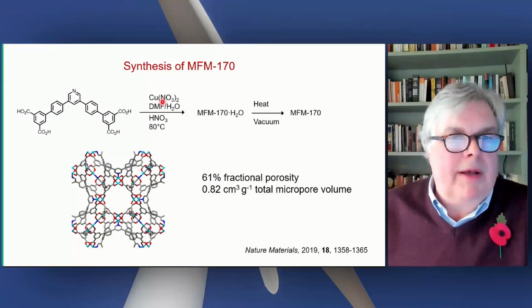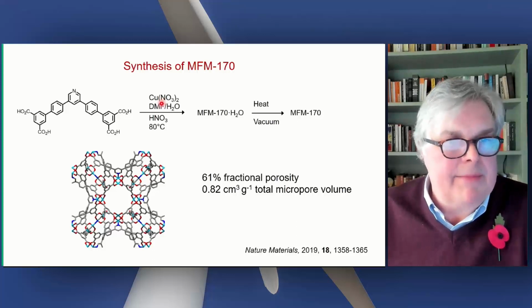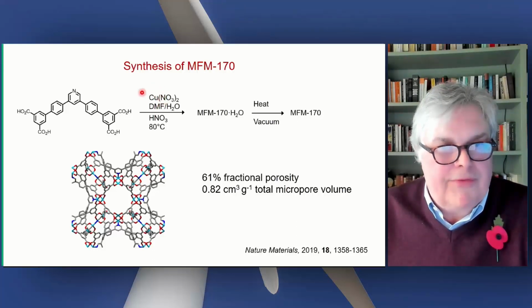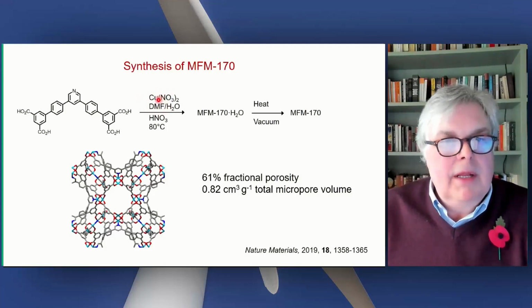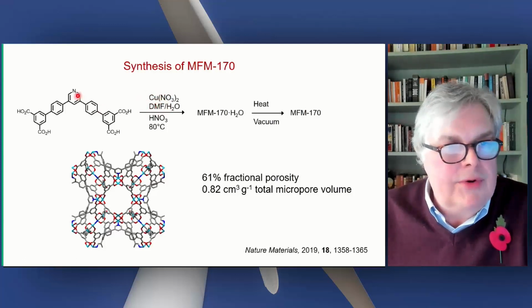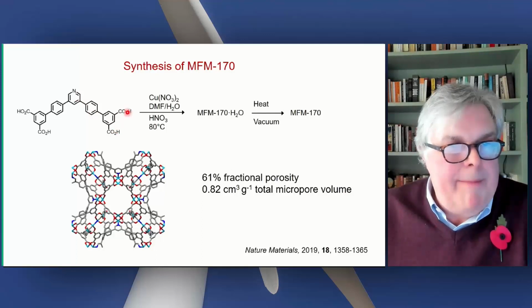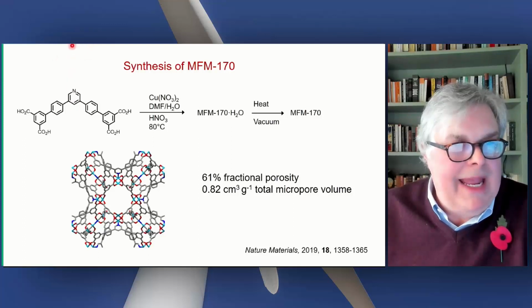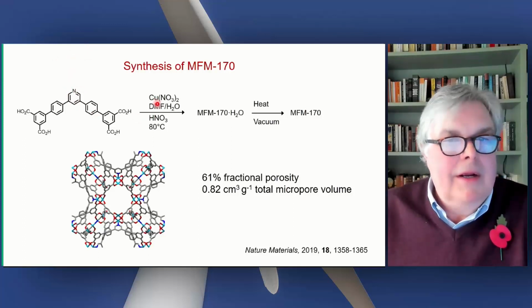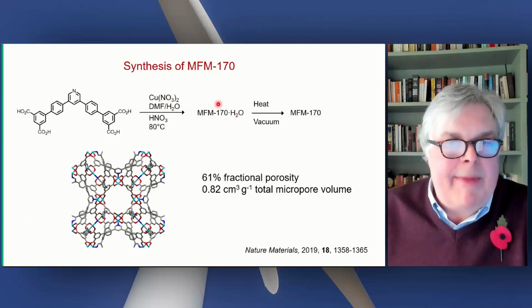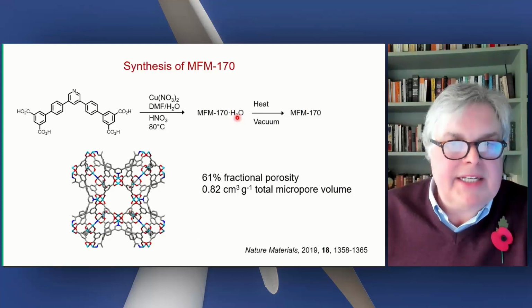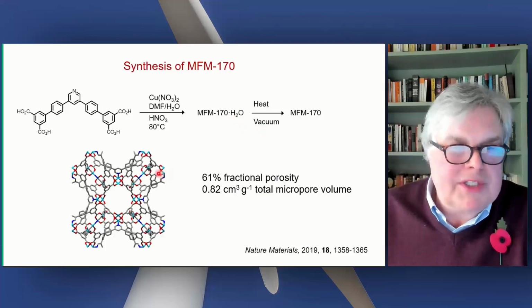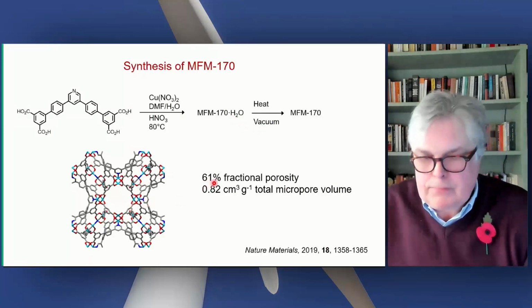This is again another copper material. It's very, very stable. This is very unusual for a copper 2 system to be so stable to SO2. The ligand we've used is tripodal again, but we've replaced this dicarboxylate group here with a pyridyl group. We form 2 compounds. One is MFM170, which has a coordinated water on a copper site. I'll show you that in a moment. You can heat under vacuum, and that removes this water and all the water inside these channels.